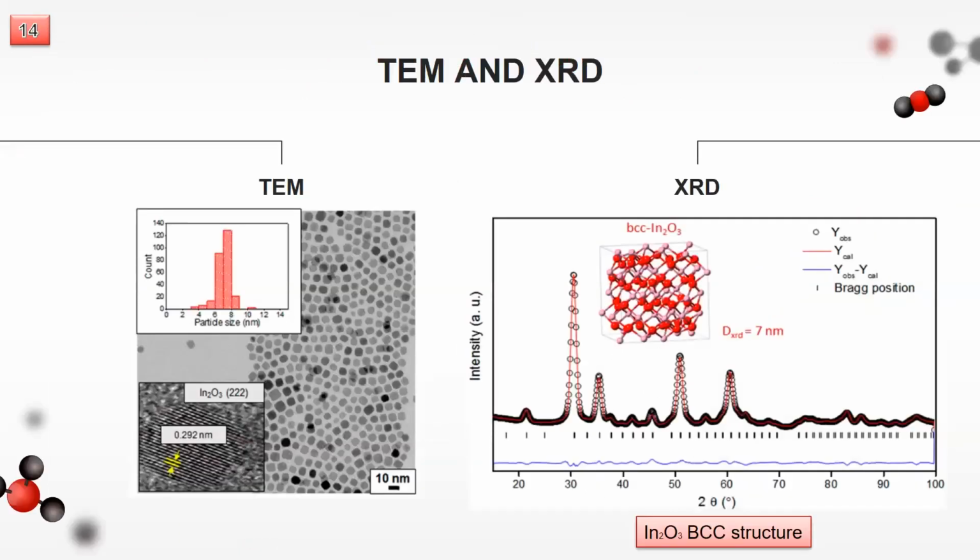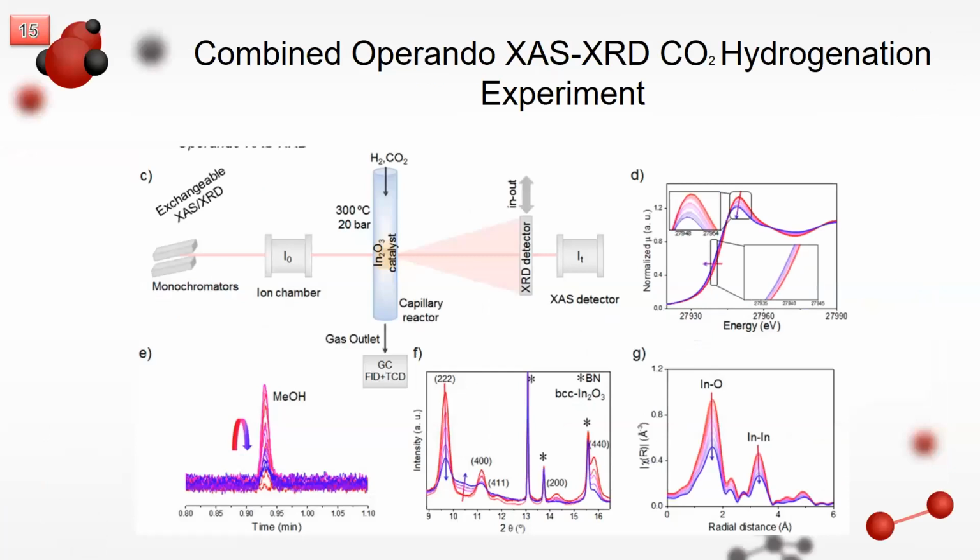In this specific paper that I am reviewing here, they synthesized indium oxide with an average particle size of 7 nanometers, confirmed by TEM, and then measured the XRD. The XRD confirms the formation of indium oxide. Then they studied in situ XAS and XRD, and the results are really interesting, as you can see in figures F and G.